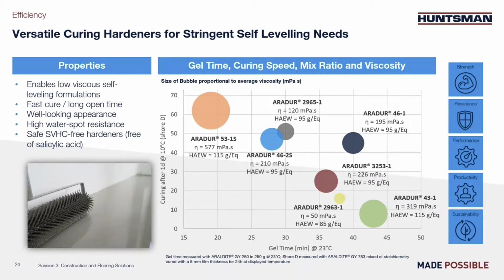So on this slide and on the next one, we want to focus on 100% solid epoxy self-leveling hardeners, and potentially also for top coat or thin coat. Those hardeners are designed in view of very good appearance, and generally speaking, the goal is to get a certain reactivity, both in cure and in gel time. They vary also in their viscosity, which enables, when very low, to add more filler and still have a very good flow, ensuring leveling. As you know, for these applications, the final appearance is key, and the hardeners are made in a certain way to achieve good appearance.